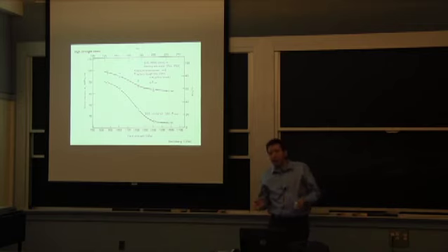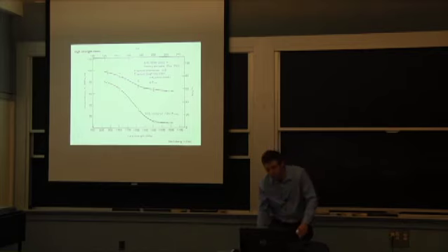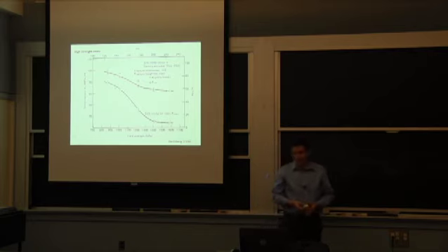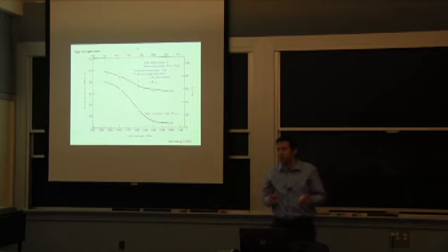Now, if you are looking at environmental cracking, it's a very different effect. So environment cracking is this lower curve here. You can see about a 5-fold decrease in the resistance to a crack that's existing if you have the environment, if you have chlorides, temperature, hydrogen over time that is locally at the crack tip. And that's how a lot of pressure vessel applications end up being decided. They'll decide, oh, we want a good purity alloy. We don't really want to go crazy with strength because we know we're going to have all these other problems if we do.